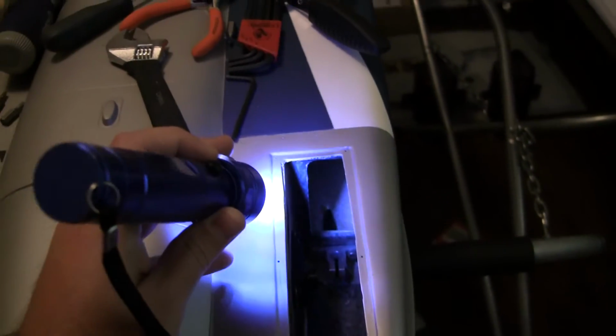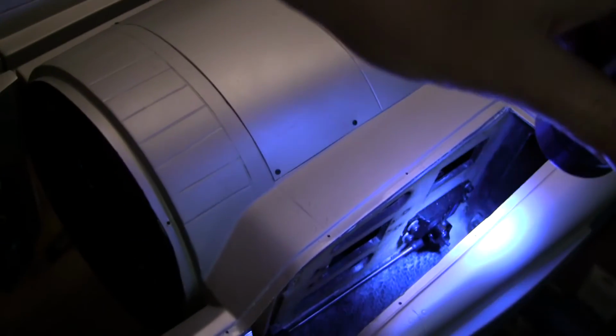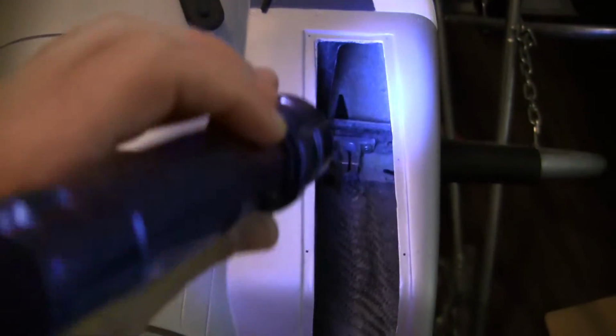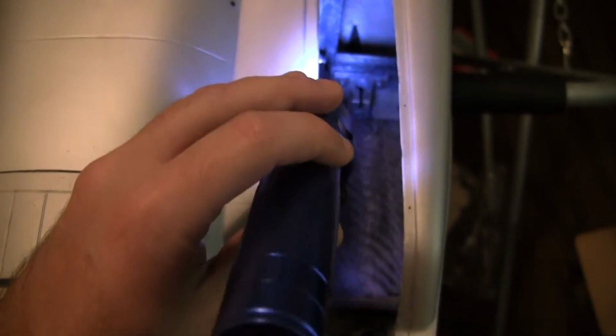I thought these were ply bulkheads initially, but they're not. These back two, you can see the ply there where the servos are in between two bulkheads, and those two bulkheads are honeycomb. There's ply on the back side of them, which does nothing. You can see the ply there on the back, facing forward, and the bolt head sits on that, but the side that the bracket sits on is just straight honeycomb, and when you tighten those two bolts, it just crushes it.